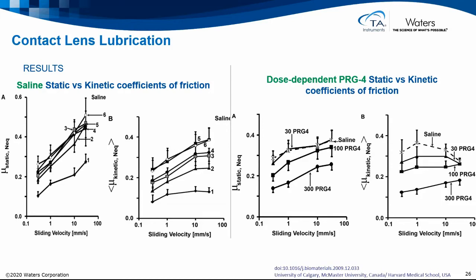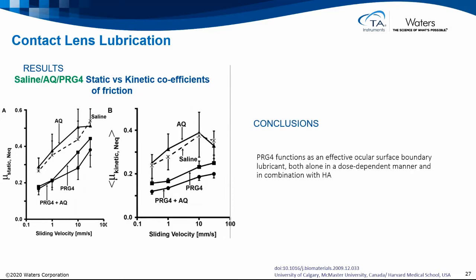escalating up in friction. Now on the right, this is looking at proteoglycan 4, and because there's another variable in here of the dose dependency, they're choosing the fourth position on the left, so that fourth wipe of that eyelid you can think of, and taking that data and putting that on those plots, but now looking at the various dosage levels of this proteoglycan 4. So you can see the higher dosage level with significantly less static friction. So you can see lots of variables here, lots of ways to plot it, and hopefully that comes across and is clear.